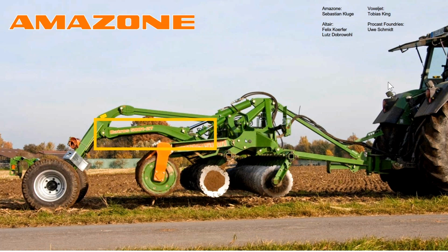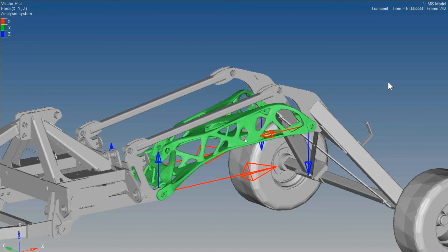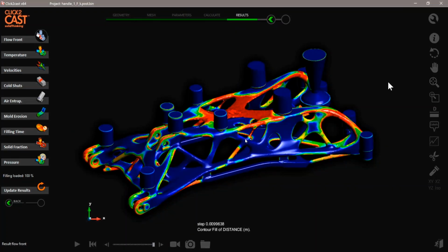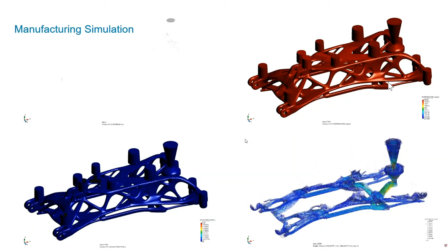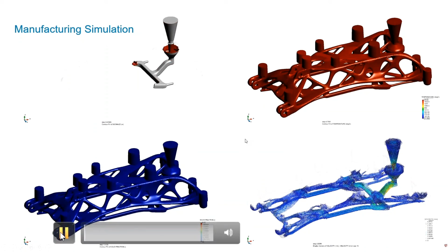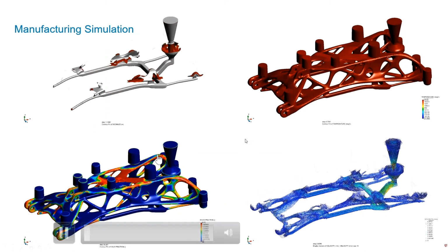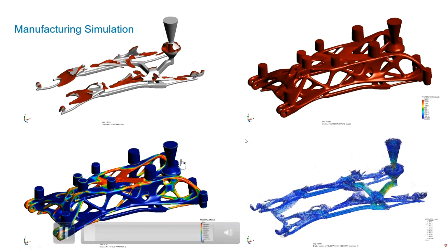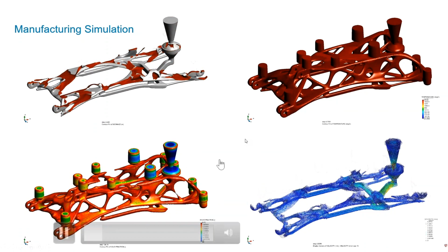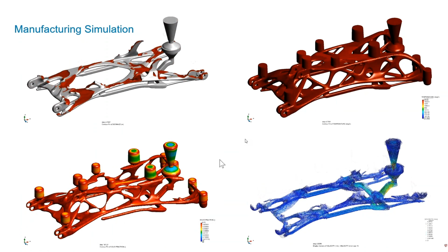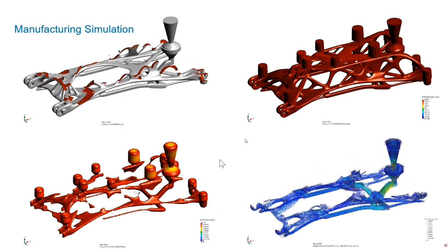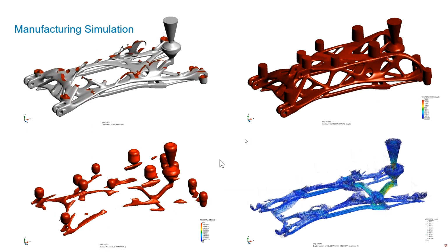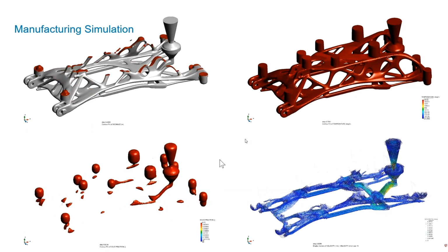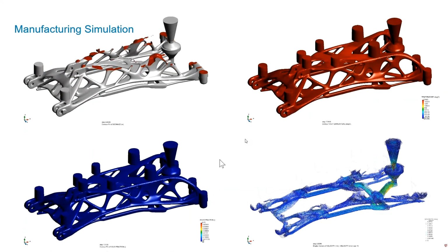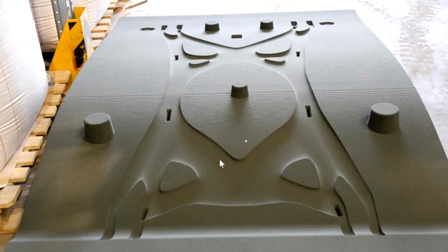We also evaluated whether this bionic structure can be cast. And we did multiple analyses on this, looking at the flow, looking at the solidification by putting multiple risers onto the structure, and whether the risers are feeding into possible areas of porosity. Once we came to a conclusion that it is possibly castable, we went ahead, and the interesting thing was we 3D printed the entire mold. In this case, we 3D printed the mold in a voxel jet printer, which is basically 3D printing the sand.